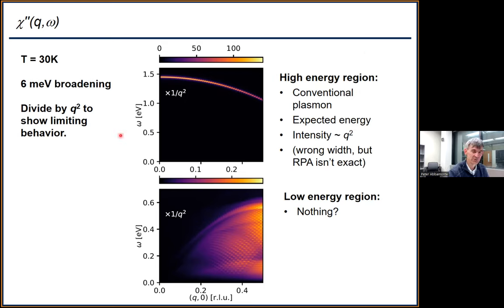Okay. Anyway, so what you calculate in RPA is chi double prime of Q and omega. And this is momentum on the horizontal axis, frequency on the vertical axis. The color is the magnitude of chi. And chi, as I mentioned earlier, goes to zero like Q squared. So what's plotted here is chi divided by Q squared. So if this thing goes to a constant color at small q, then that means that the thing's going to zero like Q squared, which it should according to the f-sum rule.